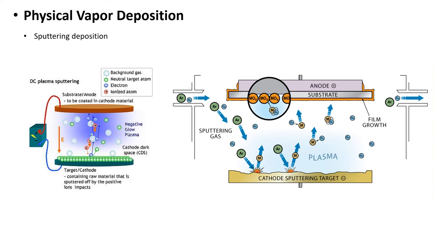Re-sputtering is re-emission of the deposited material during the deposition process by ion or atom bombardment. Sputtered atoms ejected from the target have a wide energy distribution, typically up to tens of electron volts. The sputtered ions, typically only a small fraction of the ejected particles, on the order of 1%, are ionized and can ballistically fly from the target in straight lines and impact energetically on the substrates or vacuum chamber, causing re-sputtering.